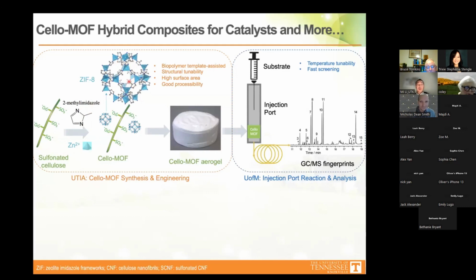And if you have heard the word, it's called metal organic frameworks. So basically it's made up of metal ions coordinated with organic ligands. And this cage structure is very special because you can tell it has a void structure in the center, and that void allows this material to have a really high surface area and a pore structure that allows it to capture, hold, and release chemicals. Then you can apply it as catalyst, absorbents, CO2 storage, air purification, and so on and so forth.